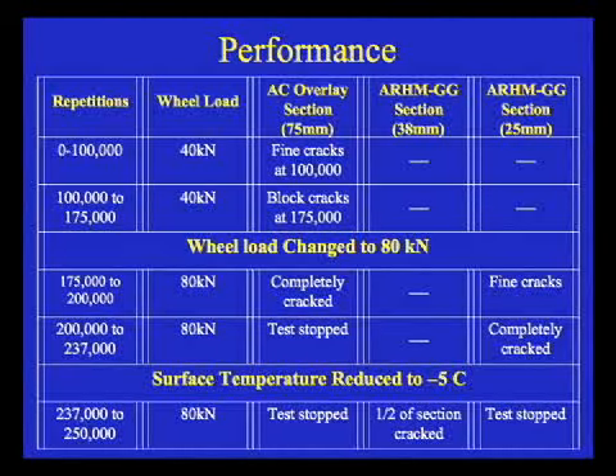So we lowered the temperature, and after 250,000 repetitions, we got half the section to crack. So 250 compared to 175. Oops, I'm sorry. The 1-inch section, the same thing happened. We got to here, no cracking, so what we did was we doubled the load, and it completely cracked at 237.